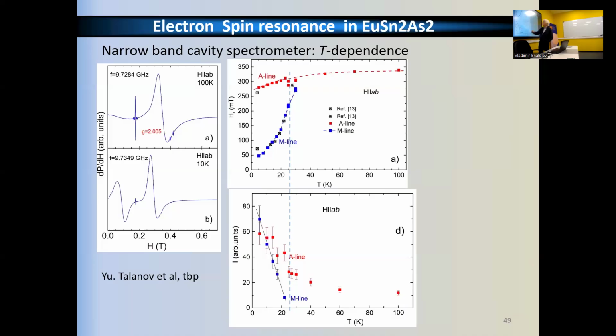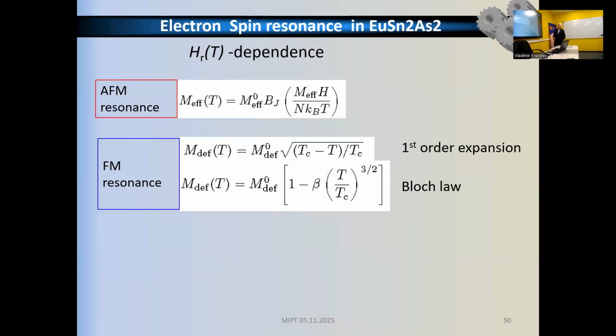So this low resonance field, or high frequency resonance, is this M line, which we try to interpret as a ferromagnetic resonance. And its intensity again drops down at the temperature of antiferromagnetic ordering. Now we apply some quite simple formulas. For the temperature dependence of the effective magnetic field of the antiferromagnetic resonance, we use the Brillouin function, which is reasonable, and it gives us the temperature dependence of the acoustic AFM resonance. And as regards the ferromagnetic resonance, we can either take the first order expansion in the vicinity of the critical temperature, which is just from thermodynamics, or, in the vicinity of zero temperature, the so-called Bloch law.